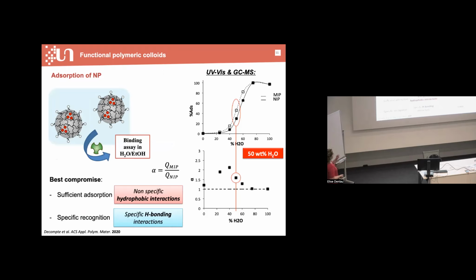And then the challenge in MIP is to provide sufficient adsorption of the template molecule while enabling a specific recognition of this specific molecule. We found that by using pure water, here 100% water, we got the higher adsorption yield. But if you check the graph below, you can see that the recognition was non-specific, because the interaction inside the NIP and the MIP is the same. This is because in pure water, only hydrophobic interactions are involved, and so the microgel is not specific of the molecule.